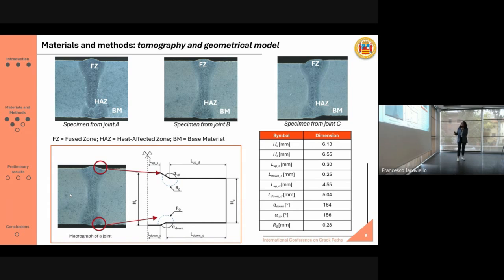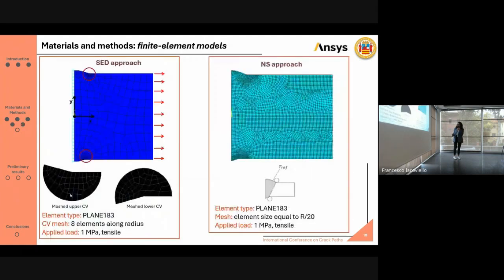Now, focusing, for example, on the specimen from joint B, by means of an image acquisition software, we were able to extract the main geometrical dimensions to construct this very simplified geometrical model. This geometrical model allowed us then to go on to the finite element model that was constructed for both the SED approach and the notch stress approach.